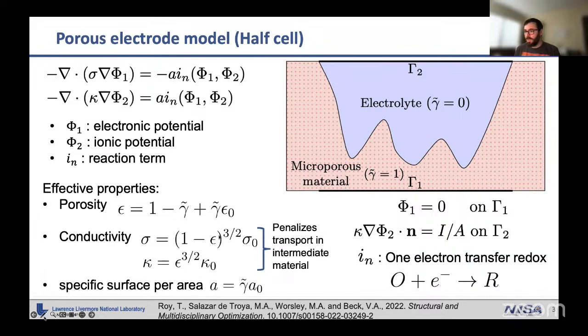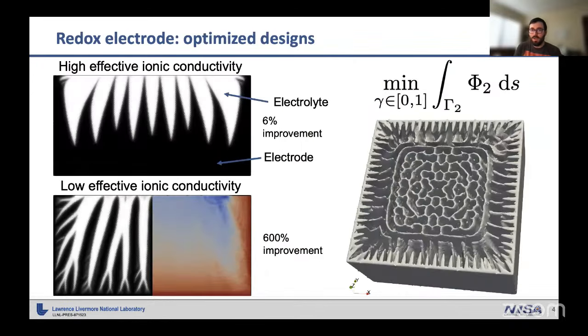And then for the specific surface area, there's no reaction in the electrolyte phase, so 0, and then it's equal to A0 in the porous material. So we apply a current at the half cell interface, so at the top, gamma 2, and then we fix the electronic potential at 0 at the current collector. And so the shapes we get will depend on the physical parameters we do.